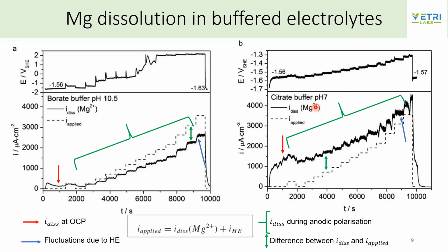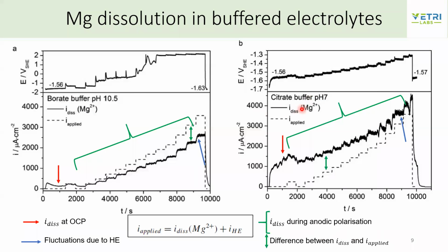With this, they concluded that in the case of higher pH, the film that forms is very stable, and it curbs metal dissolution. Whereas in the case of citrate buffer, they have higher dissolution and a completely different passive film, which does not support, rather enhances, the magnesium dissolution.